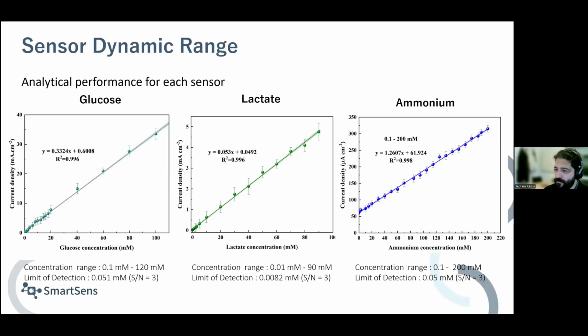Just to show you some of the results for our 3 measurements of glucose, lactate, and ammonium, they show the dynamic range. It's very linear. So you see the current density versus the concentration of the analytes. For glucose, we can measure from 0.1 to 120 millimolar, a very straight line. Similar to lactate, 0.01 millimolar, very low concentration, all the way to 90. And for ammonium, it's actually up to 200 millimolar. So very broad dynamic range, and this is actually exceptional. And the linearity is also very high.